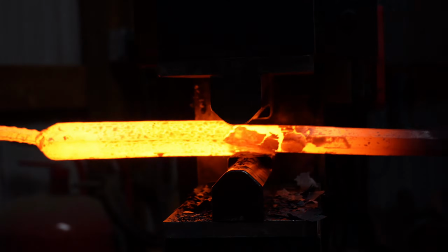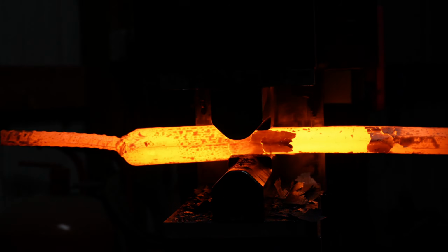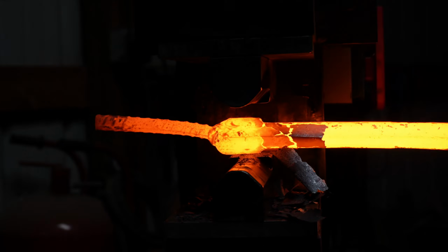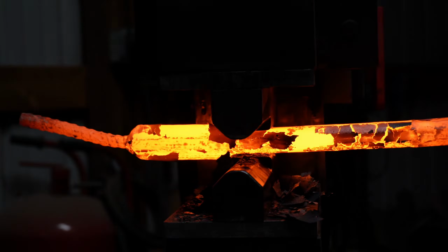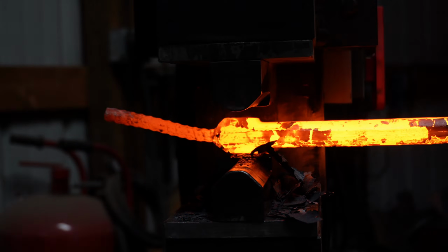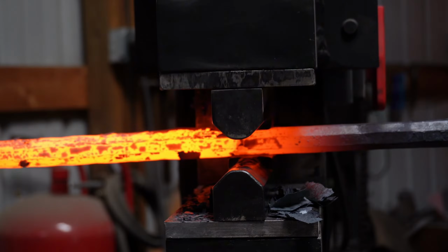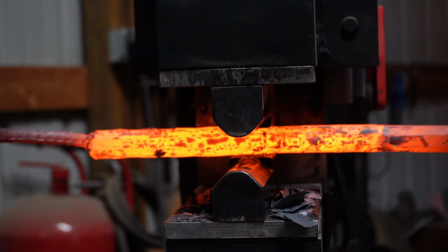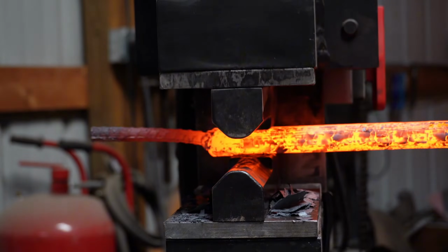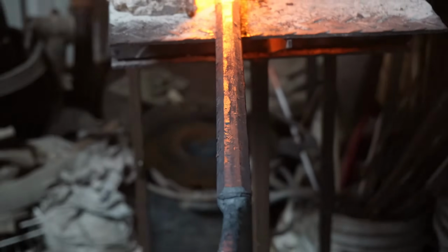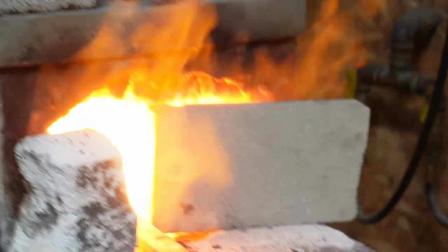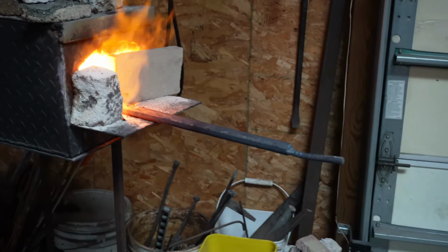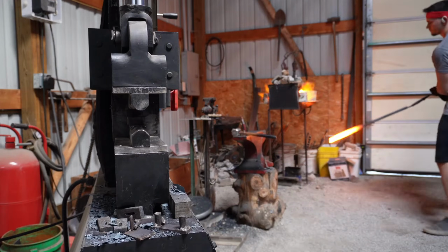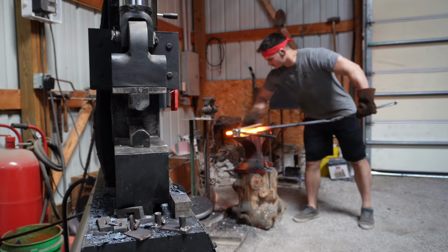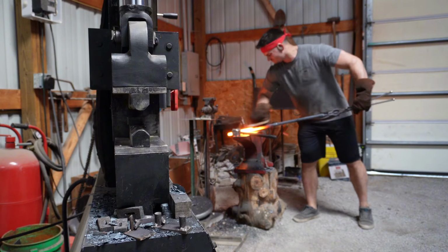So as you can see here, I've gotten my billet drawn out into a really long square bar, and now I'm breaking the corners to make it into a round bar. This is because when you're twisting, if you have those big corners protruding, they create cold shuts, which makes it even more difficult to flatten it because they risk splitting open. This bar is massive, and my plan is to basically mark the center point, twist one half one direction and the other half the other direction to give us our alternating twist multi-bar pattern.